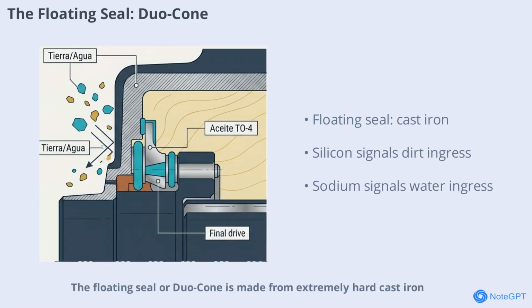Floating seal or Duo-Cone is made from extremely hard cast iron. Unlike other components, a failing seal doesn't warn with metal particles but rather with environmental ingress. Elevated silicon over 15 ppm signals dirt or silica, while sodium over 20 ppm indicates water or humidity. Monitoring these elements in oil analysis helps detect seal failures early, protecting the final drive from contamination.